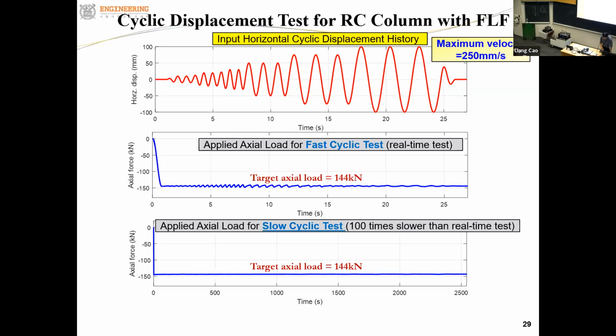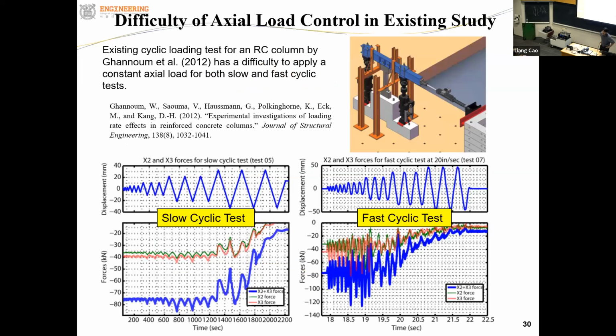And this is the case for the slow cyclic loading test. You can see that it's almost perfectly constant loading applied during this cyclic loading test by using this new force control algorithm and the flexible loading frame. So this kind of force control is very difficult to achieve in existing tests. That is the test conducted at the University of Colorado. Similar test setup as we had, but they have difficulty in actual force control.